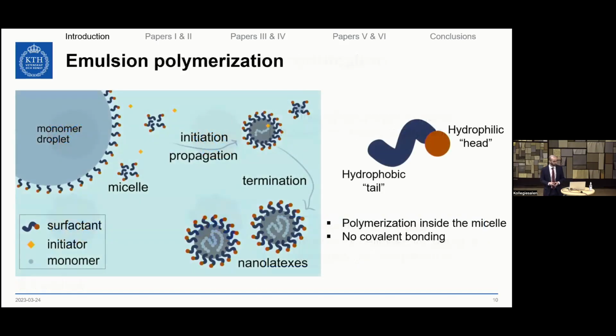Typically, these polymeric nanoparticles, commonly known as nanolatexes, can be prepared via emulsion polymerization, where we have low molecular weight surfactants, which are comprised of a hydrophobic tail and a hydrophilic head. And when dispersed in water above a critical concentration, we can get these micelle structures. And inside the core of those micelles is where the polymerization of a hydrophobic monomer takes place. However, there is no covalent bonding between the hydrophobic core of those micelles and the hydrophilic shell that covers them.